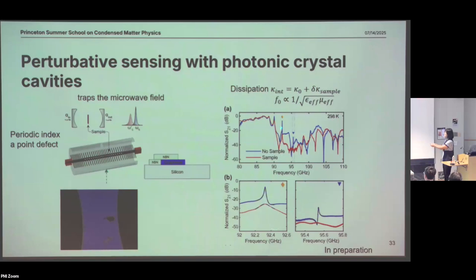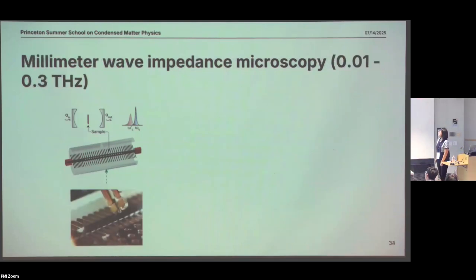As you can see, there's a little bit of frequency shift. These are the zoom-ins at specific frequencies of the resonance. And then there's a shift, and also the peak broadens. And so that's a type of measurement to say that the sample caused more dissipation. Okay, so this is a measurement where we try to increase the sensitivity of the transmission.